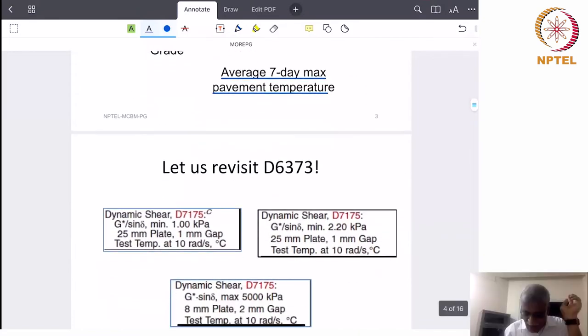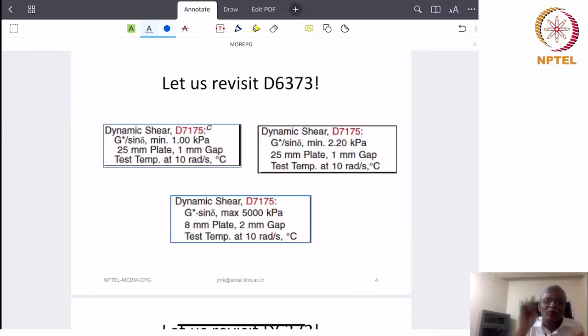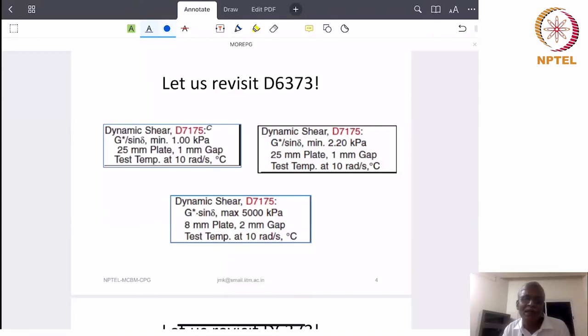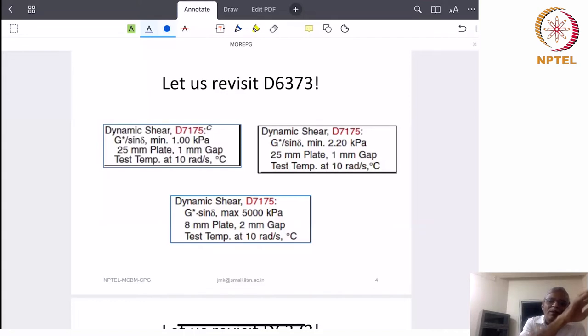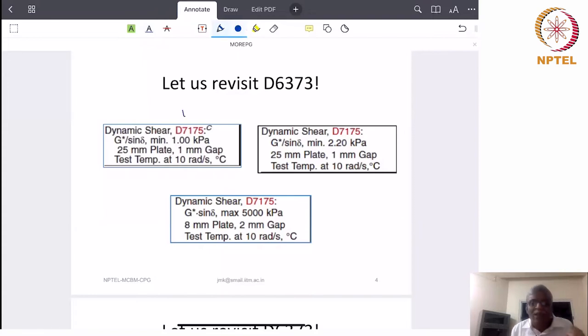Let us revisit ASTM D 6373 in a little more detail. What you see here on the first column — I emphasized this earlier — in viscosity grading you see the parameter, temperature, and value on the right-hand side. In performance grading, what we really do is flip it. The parameter and values are there and the temperature comes on the right-hand side, because the emphasis is on the temperature. What it basically says is: dynamic shear D 7175 is the standard we are going to use — G* by sin delta.